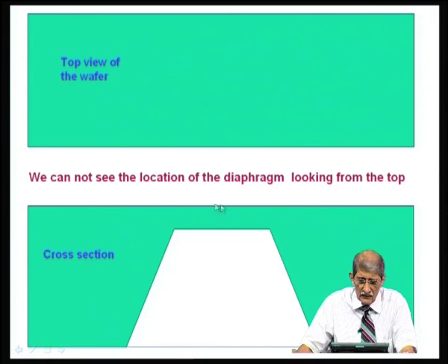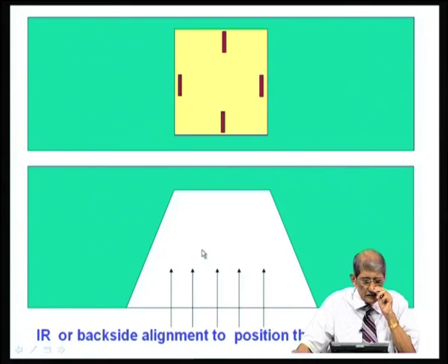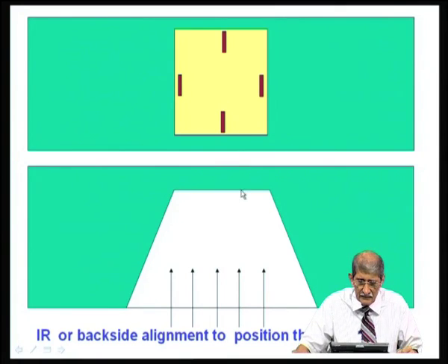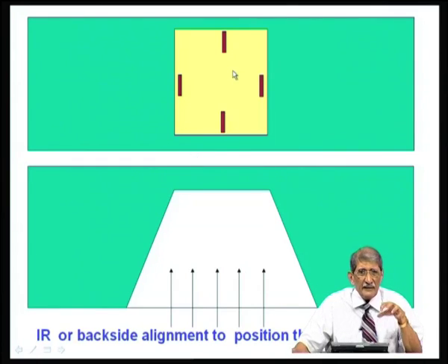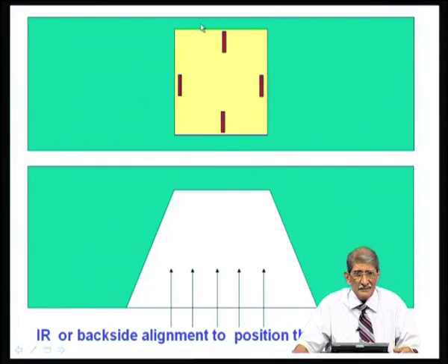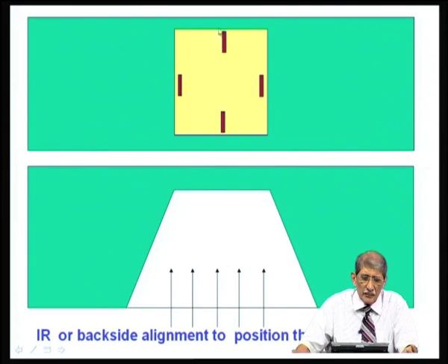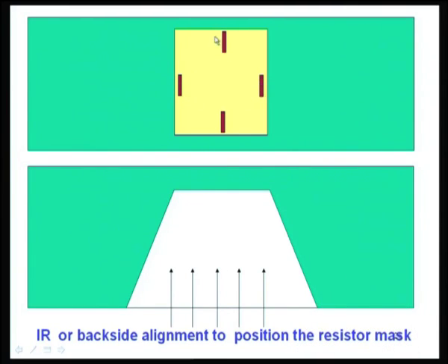See, you want to put the resistors on the top of this membrane, for that you will do lithography, you must see it from the top. When you see, you must see where the membrane location is. One way of doing that is to shine infrared light, IR light, from the back side of the wafer. Then you can see this particular thing transparent like that, because IR can go through from the bottom, and if you put a video camera on the top, you can see this membrane. Okay, I have shown this, and then by lithography technique from the top, you can grow oxide, open windows in the oxide in these portions and diffuse resistors here. That is the technology part of it.